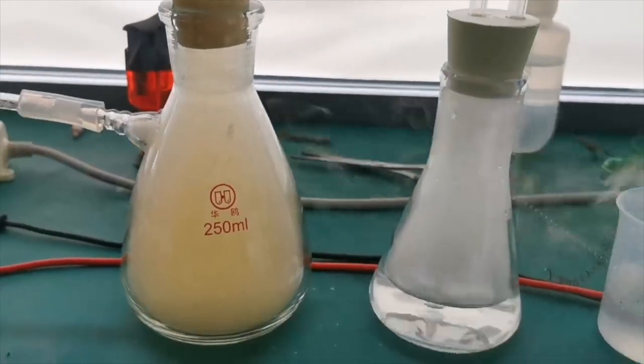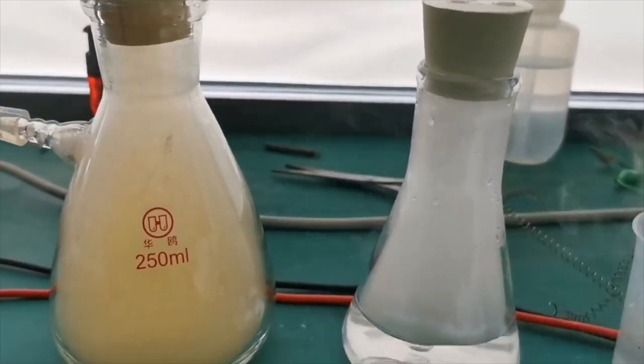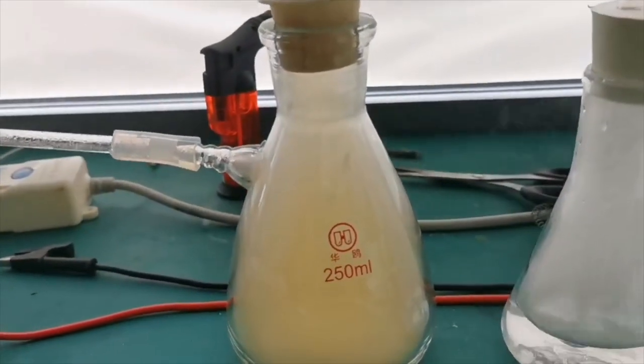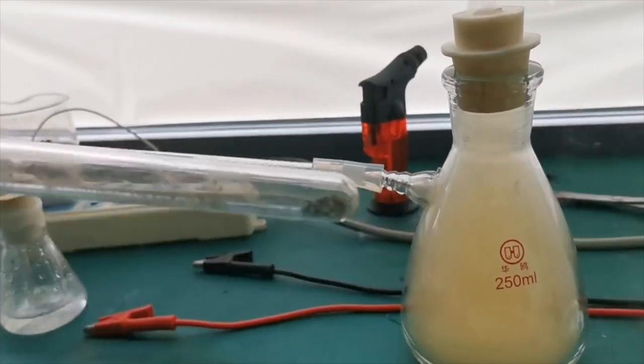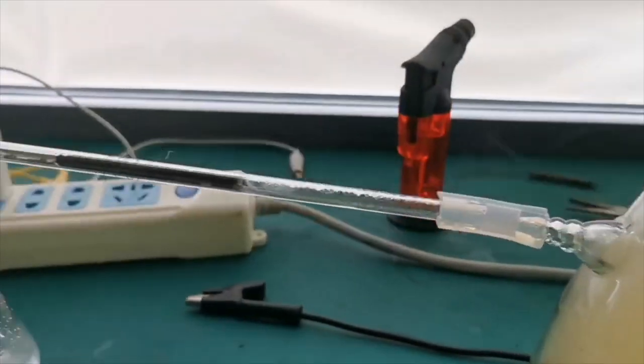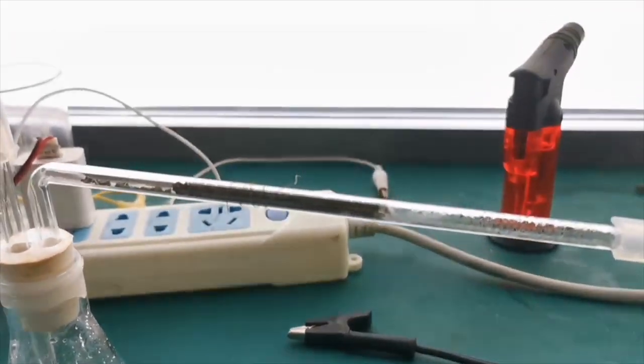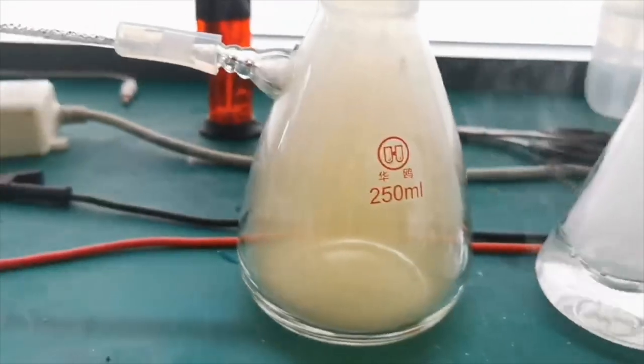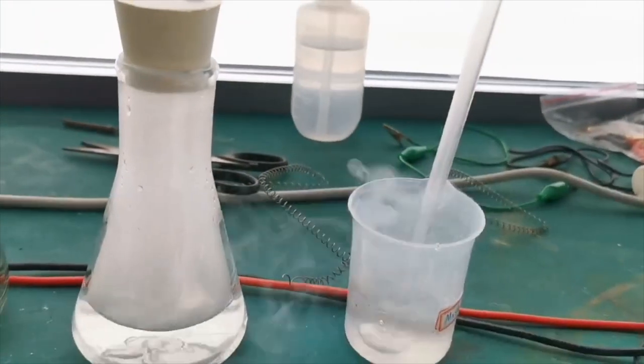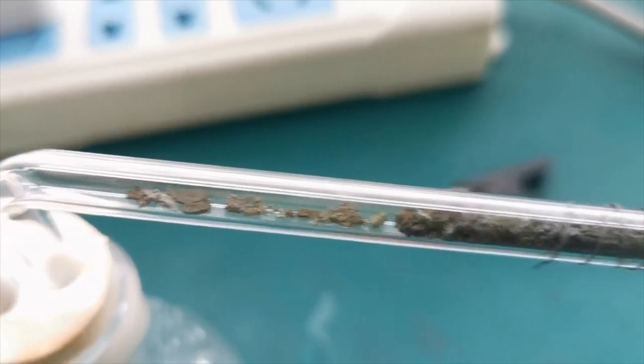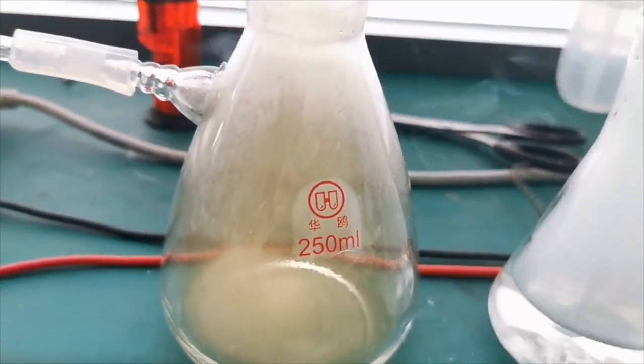Yes, I finally got it to work. I exchanged the catalyst to be some chromium oxide that I made by decomposing some ammonium dichromate in the test tube, which you can see is here. I filled this chromium oxide inside this normal glass tube, and then I lightly heated it with a blowtorch, and guess what? The reaction started. And already you can see a bunch of fumes being produced. The yellow fumes are obviously the nitrogen dioxide, and those white fumes are actually the ammonium nitrate from the solution, from the reaction. I don't even have to keep the heating.